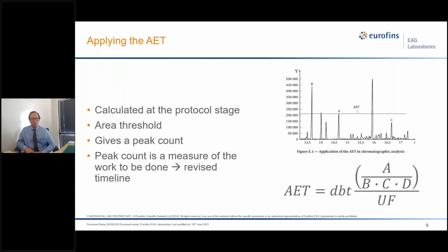So we've talked a couple times about the AET, right? I mentioned it in the discussion of the protocol, and Melissa touched on it as well, and making sure that it's appropriate to the device. So now that we've made sure it's appropriate and we've done the preliminary calculations, now we need to examine it and apply it specifically to our instrumental techniques, right? So we've already calculated it as a concentration in solution, right? Now we need to convert it to an area threshold.